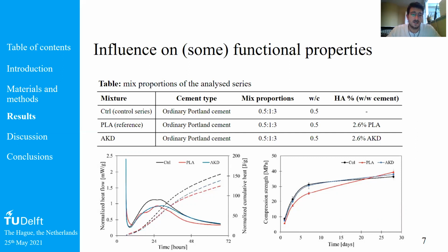As we can see in the bottom of the slide, the hydration curve of the cement paste including AKD healing agent is a little bit lower than the one of plain mortar, but that doesn't really have a negative influence on some functional properties, such as the compression strength, as you can see on the right. It's just a little bit lower at the very first days than the compression strength of the plain mortar, but at 28 days it's even a little bit higher. That is already pretty positive, because we checked that the healing agents that we include don't really have a negative influence on some very important functional properties of the mortar.